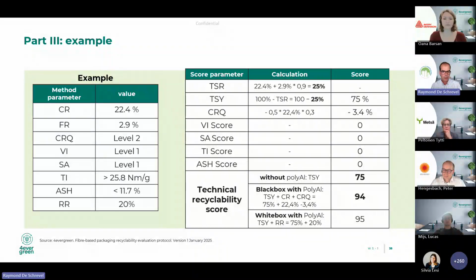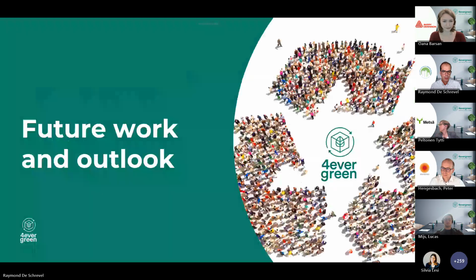If you use the black box, meaning you measure everything, including the quality of the polyAl, you will end up with 94 points. And if you use the white box or using your data sheet input, you can score 95 points, meaning that, yes, you can have a very high score, even if your packaging is not 100% paper. And that's, I think, one of the big advantages and the improvements of this methodology, that you can include also the other materials that are recycled. And we told many times that there's future work to go, but I will give back to Titi.